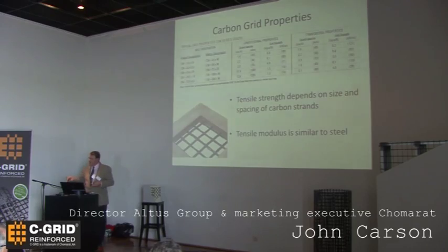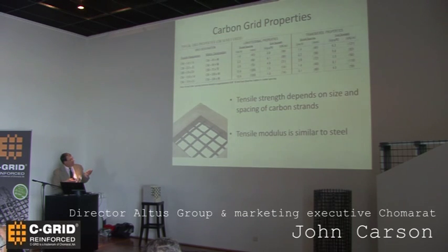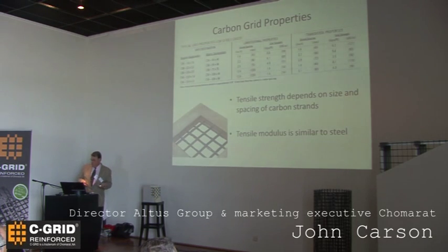In your sheets on your chairs are typical properties of some of the various carbon fiber grids I detailed earlier, the different aperture spacings, which range from 45 by 40 up to 320 by 60. So again, we're trying to develop the right type of structure for the specific type of application. The tensile strength depends on the size and the spacing of the carbon fiber strand. And the good thing about carbon fiber composites is the modulus is very similar to steel, so it makes it easy to design and replace from an engineering standpoint.